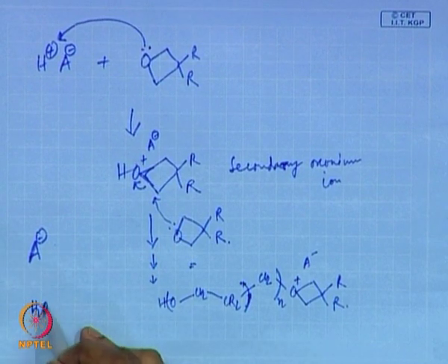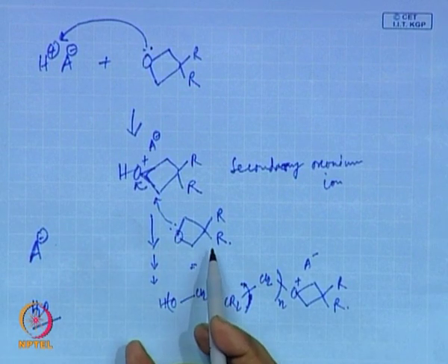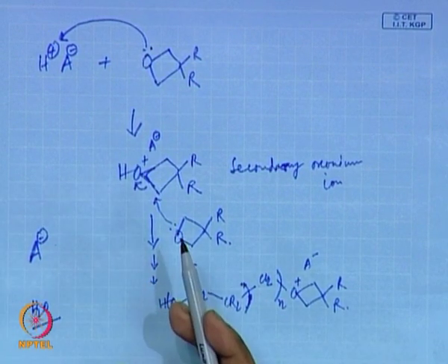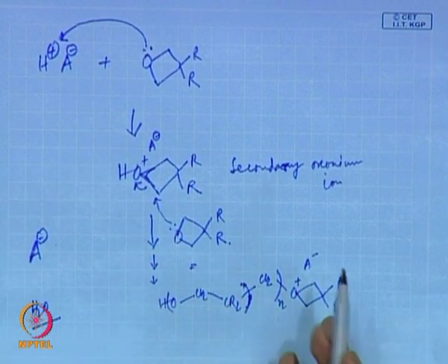Similarly, if you have a little bit of moisture present in the medium, or a water molecule, then this will easily compete with your monomer for the oxonium ion and then terminate or disrupt the reaction immediately. So, like earlier when we talked about cationic polymerization, here also you have a very stringent requirement that you do not have any moisture present in the system.